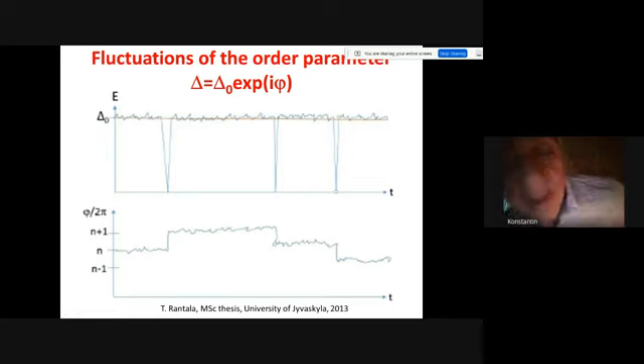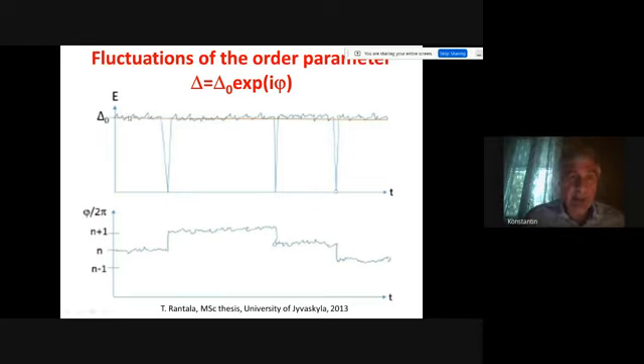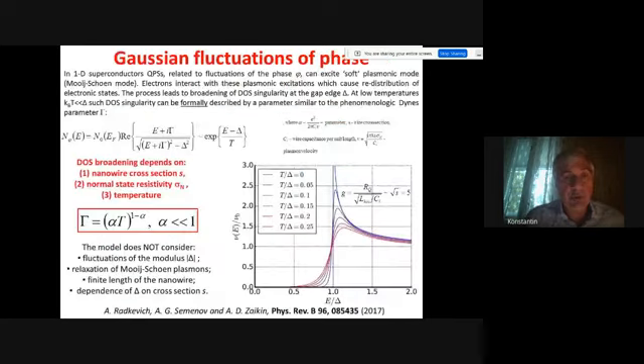So, superconducting order parameter is a complex value which has modulus and phase. And as I tried to convince you, both the modulus and the phase can fluctuate. So if to plot, let's say, energy as a function of time, it fluctuates along some value corresponding to mean field order parameter, but from time to time it rapidly drops to zero and then again fluctuates. And this process is accompanied by abrupt change of the phase by plus minus 2 pi. And particularly these type of fluctuations I mainly discussed before, quantum phase slips. But as you might see, there are also small fluctuations, these ripples. And these are so-called Gaussian fluctuations, and I'm going to speak about them.